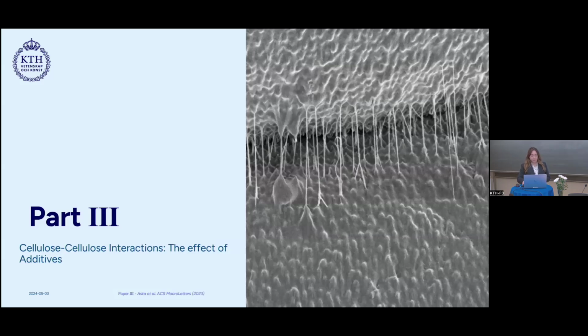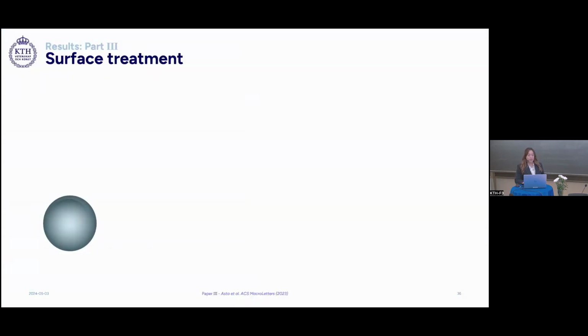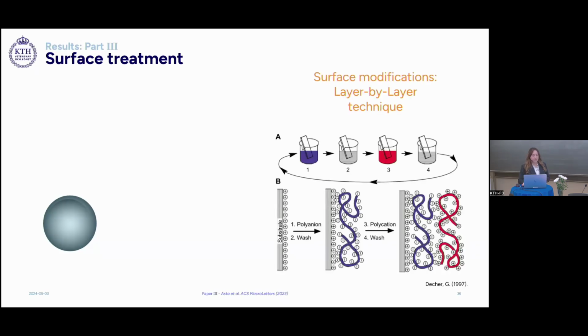Now we move on to part 3, where we study the effect of additives on cellulose interactions. In order to examine how additives will affect cellulose materials and how surfaces will come in to join together, we used layer-by-layer technique to adsorb oppositely charged polyelectrolytes on the surface of the gel beads.